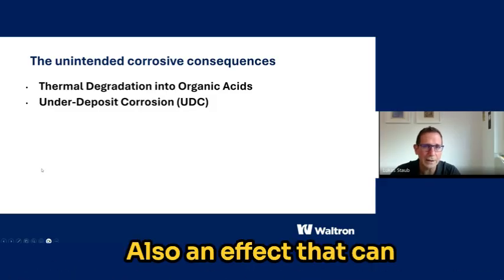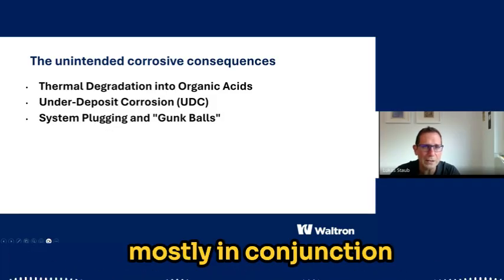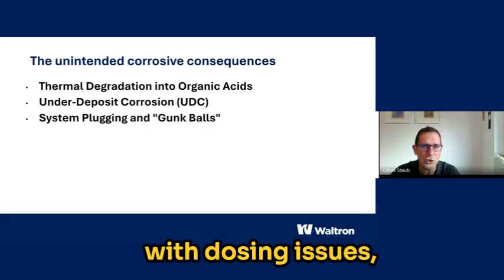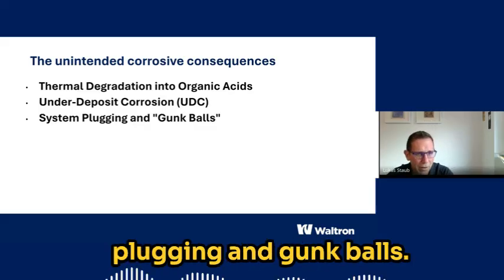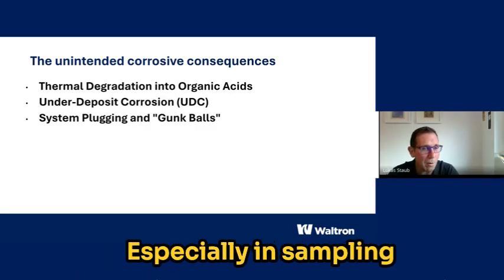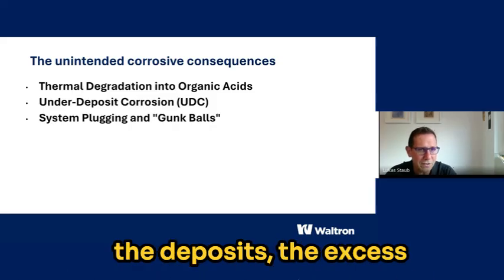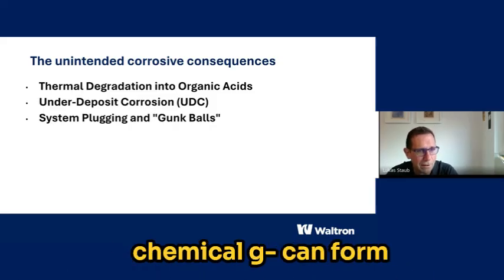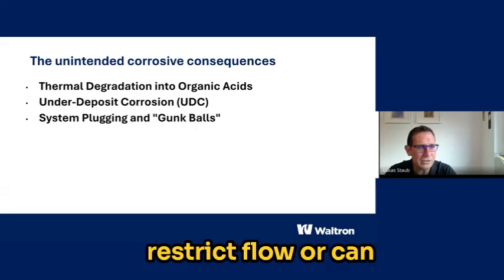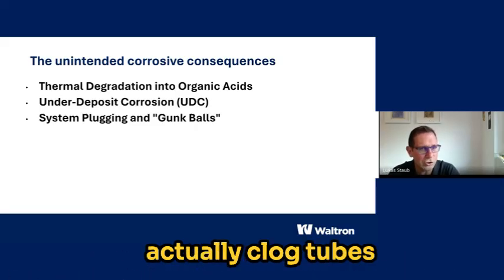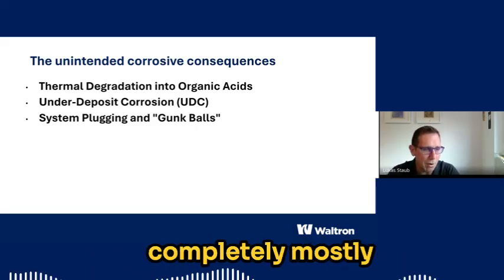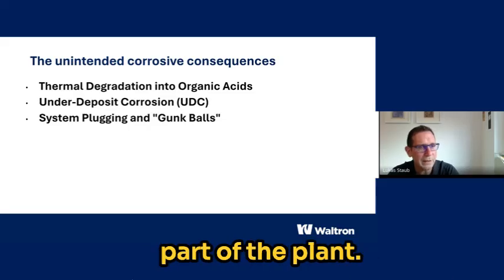Also, an effect that can be frequently seen, mostly in conjunction with dosing issues, is system plugging and gunk balls, especially in sampling lines. You will find that the deposits, the excess chemical, can form sticky gunk balls that restrict flow or can actually clog tubes completely, mostly in the low pressure part of the plant.